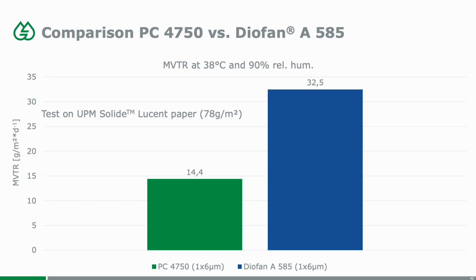And we are testing here the MVTR at tropical conditions, so 38 degrees centigrade, 90% relative humidity. And we've changed the substrate, pay attention. In this case, we are using the UPM Solide Lucent paper with 78 grams per square meter. And the result speaks for itself. You can see that the PC4750 now, when it's used on a proper substrate, we are able to achieve as low values as 14 for the MVTR, where the Diofan is at 33 roughly.